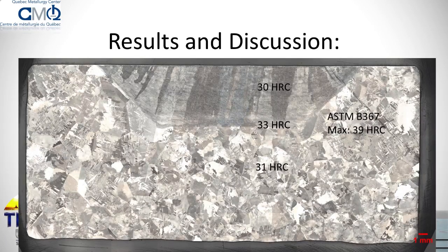It's quite bright here, but you can see a very sound repair with columnar grains in this case. It's a very good microstructure with hardness well within the requirements for casting, where the maximum is 39 HRC, and in all these cases, be it the actual repair, the interface, or the bulk material, we're far below this value.